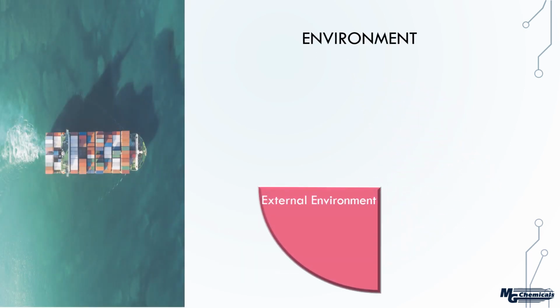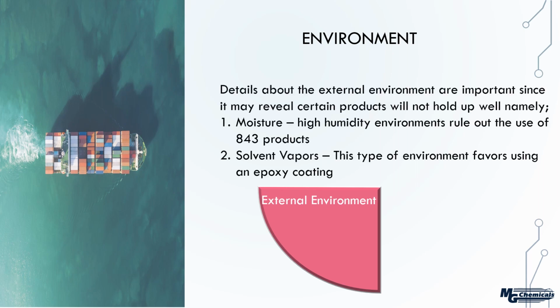Next, we want to look at the external environment. And with that, we want to look at two main things. One is we want to look at how much moisture is present in the environment. So if it's a freighter out at sea with high salt water content, that basically rules out the use of the 843, the silver-coated copper. And the reason is that over time, this moisture will corrode that product. And once it corrodes, it really starts to lose its conductivity and shielding performance.